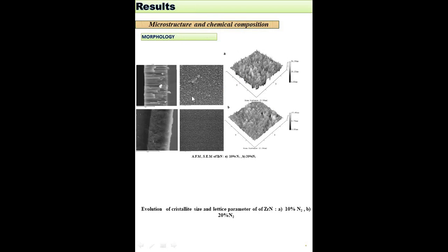The morphological analysis of the zirconium nitride thin films showed that with increasing nitrogen flow rate from 10 to 20%, the zirconium nitride coatings revealed a compact columnar structure with small grain size.